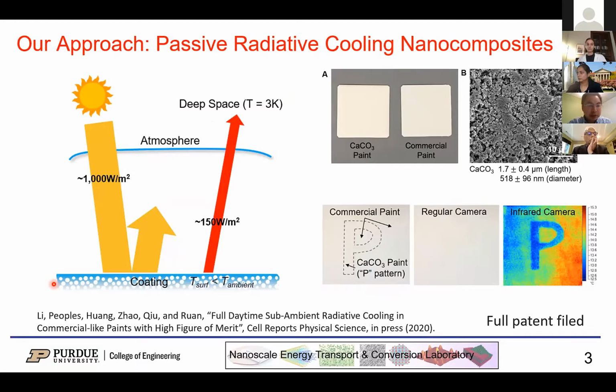We developed this coating, which is basically a polymer embedded with nanoparticles of different shapes and sizes. What this coating does is reflect almost 100% of the sunlight. At the same time, it emits heat to deep space, because this heat can penetrate through the atmosphere. So in the overall energy balance, your surface loses heat, and hence it can be cooled below the ambient temperature.